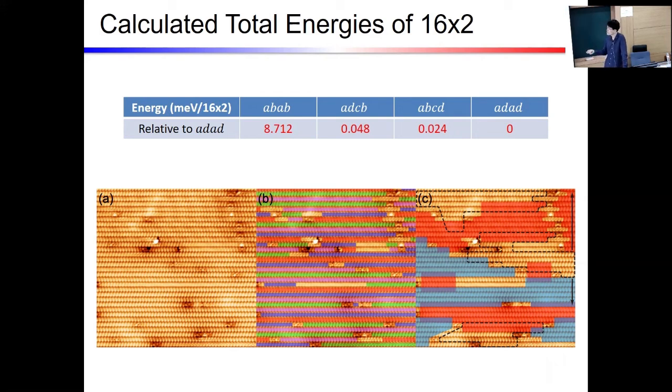Experimentally we can also find that in this structure the domains are intertwined with each other. The red is the right chiral form over here, and the blue is the left chiral form. The dashed line in the uncolorized region is the achiral region. So they coexist, intertwined with each other. But I emphasize that although this structure looks the same, an energy difference is not allowed in the real system.